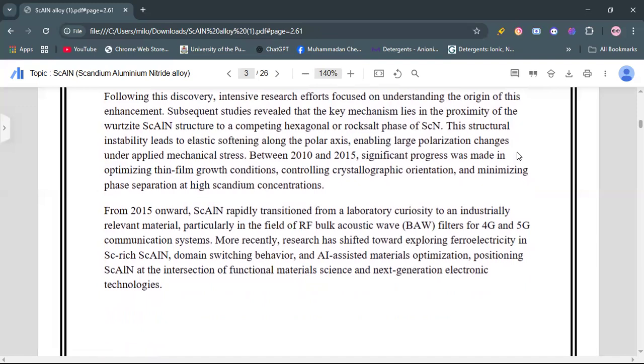Between 2010 and 2015, significant progress was made in optimizing thin film growth conditions, controlling crystallographic orientation, and minimizing phase separation at high scandium concentration. From 2015 onwards, scandium aluminum nitride rapidly transitioned from a laboratory curiosity to an industrially relevant material, particularly in the field of RF bulk acoustic wave filters for 4G and 5G communication systems. More recently, research has shifted toward exploring ferroelectricity in scandium aluminum nitride, domain switching behavior, and artificial intelligence-assisted material optimization.